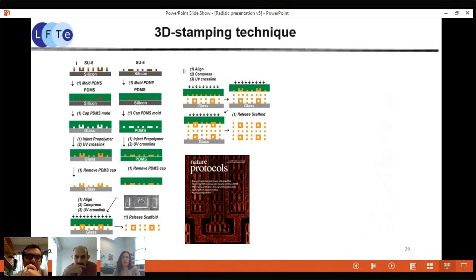And because POMAC likes POMAC better than PDMS, it will actually, after cross-linking, remain stably cross-linked. The layers will remain stably cross-linked. And this enables you to build the structure in the Z direction. So we have a pretty good control of building the structure in X, Y, and Z directions.